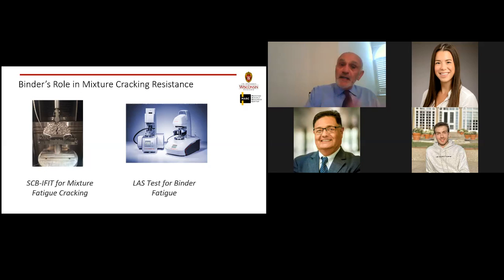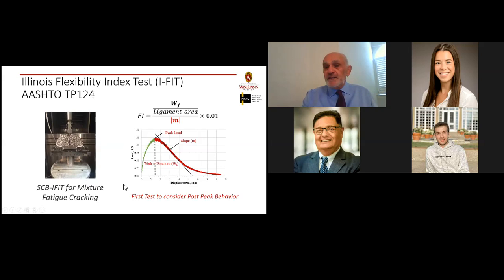To select a good test, of course, we evaluated many tests, and we selected the I-FIT procedure for this study. I just showed you the LAS test and the strain sweep, the LAS test. It is exactly the same as you see here in the I-FIT procedure. And in the I-FIT procedure, and I don't really need to explain this to you, you are the people who developed it, you have the energy divided by a slope m, which is a characteristic so well selected to describe the crack propagation.